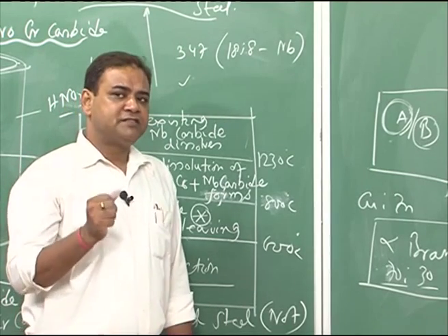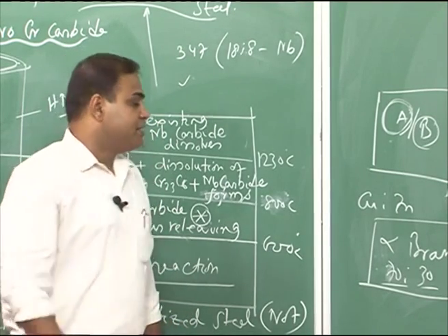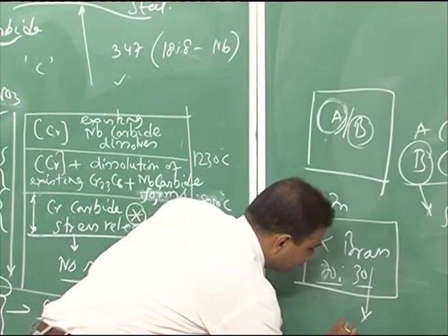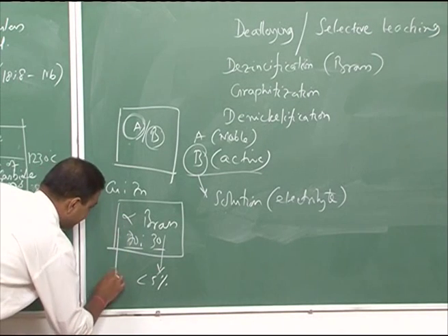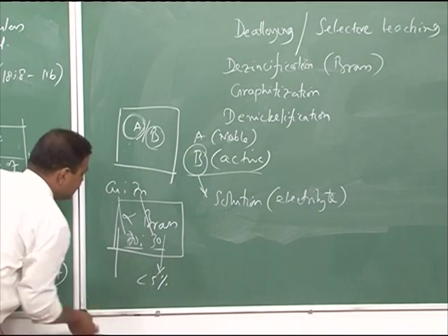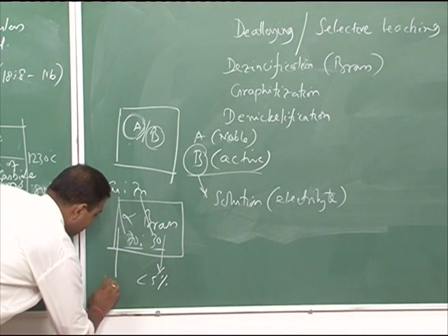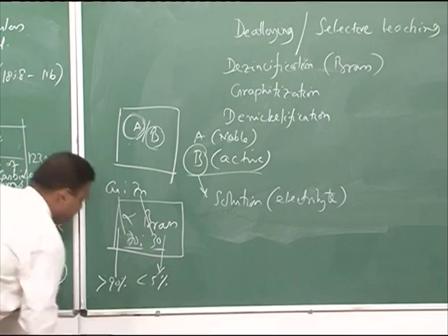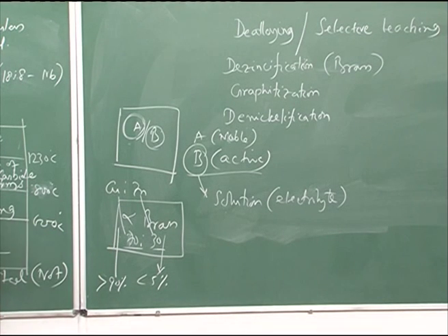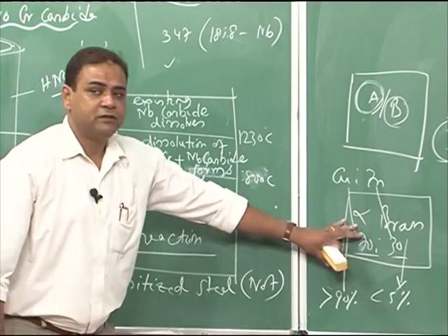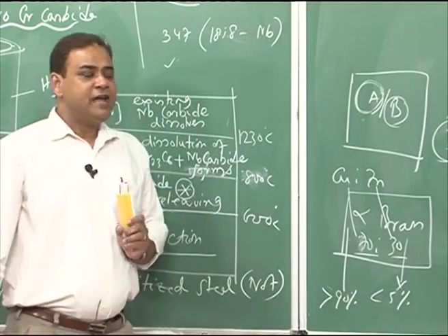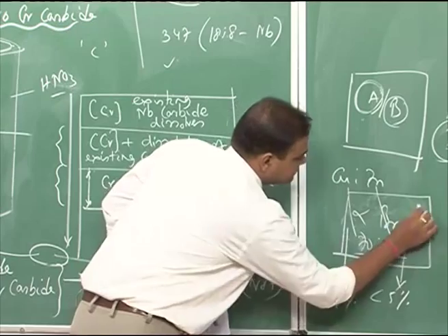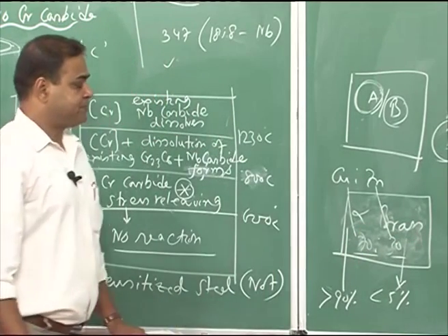If we do composition analysis of that part, we will see that zinc content has gone down, even to less than 5%, and the copper content around that zone can go beyond 90% from 70%. So, here we see the zinc is dissolving preferentially, leaving the copper in the material. So, copper content increases and zinc content decreases, and over the surface we will see the reddishness increases.